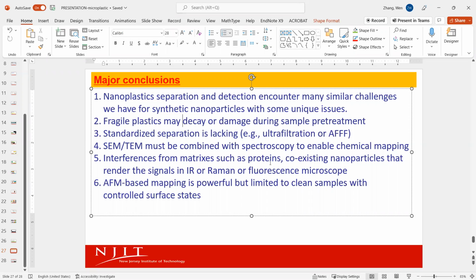Interferences from matrix, coexisting proteins and nanoparticles could render IR, Raman and fluorescence signals that largely prevent us from accurate quantification sometimes. And the AFM techniques, even though very powerful, as you see, very fancy, showing us a diversity of functionality, are constrained, I would say, to laboratory conditions. When you deal with environmental samples, it's really, really hard to operate.